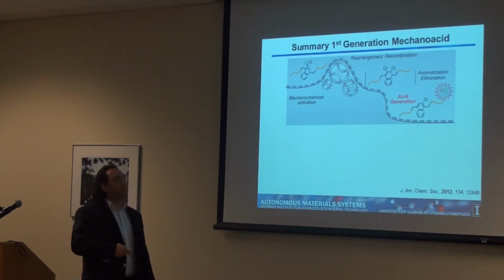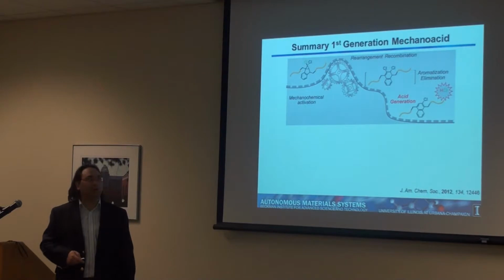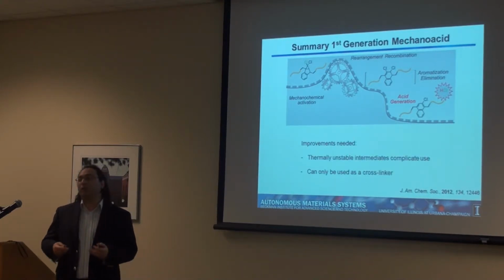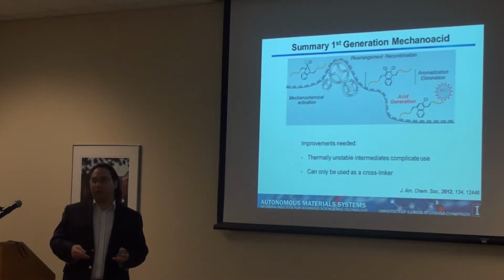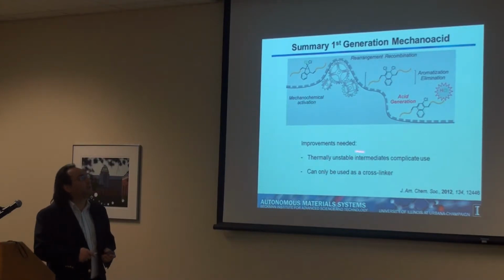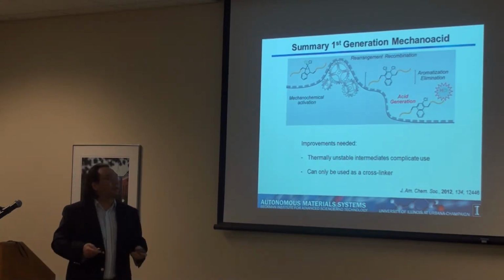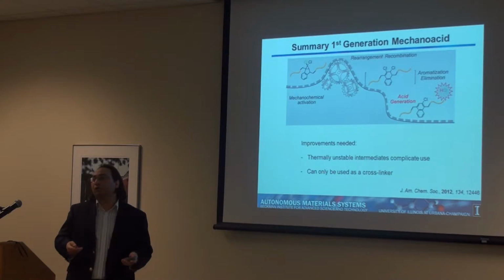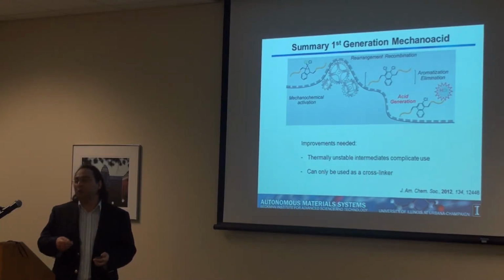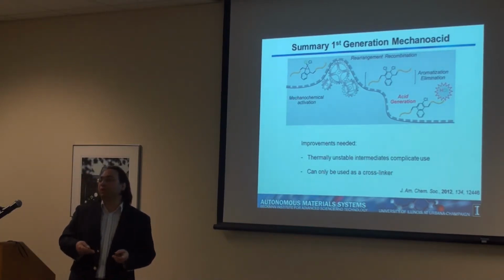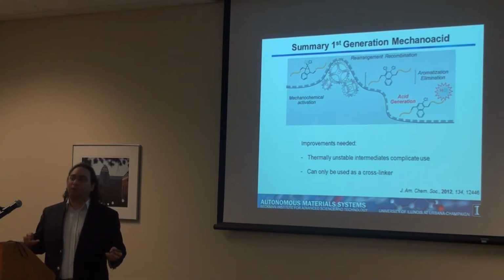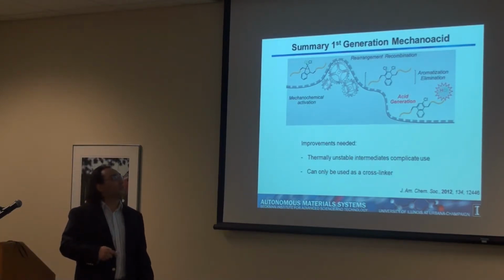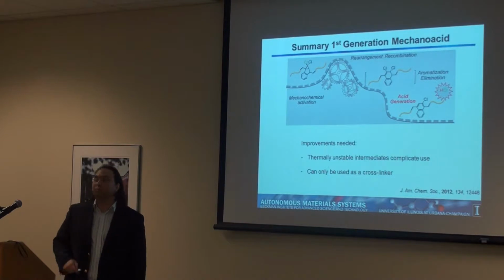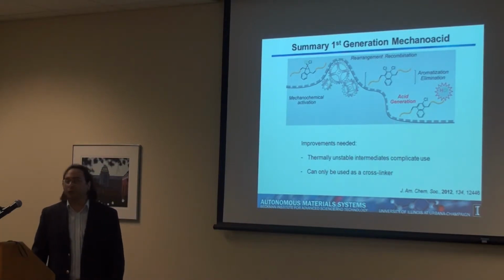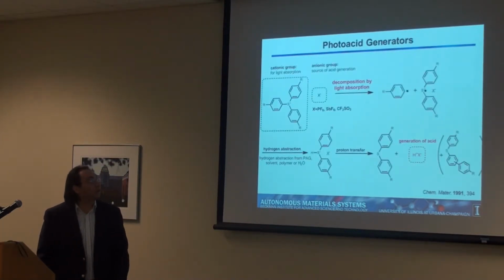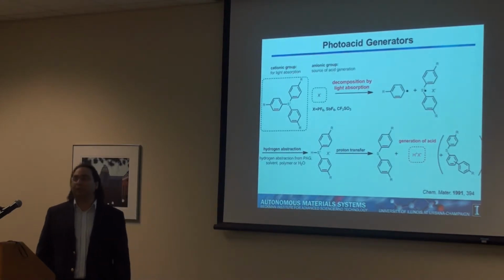Now this was a very good, nice proof of concept, but it's still not good enough for real life applications, and that's mostly because it's thermally unstable. So the control showed 5% activation. You don't want to have 5% acid being produced during the lifetime of your compound just thermally. So we need a more stable system that can live for a longer time. And for that, we went to develop a new mechanogenerating acid.